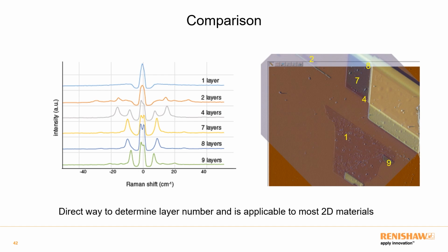But what we've got here is a really nice tool where we have these very distinct band setups for different layer thicknesses, and we can use that to image quickly across a whole sample and determine what the layer numbers are in a given location. And that's what I'm going to show you on the next slide.